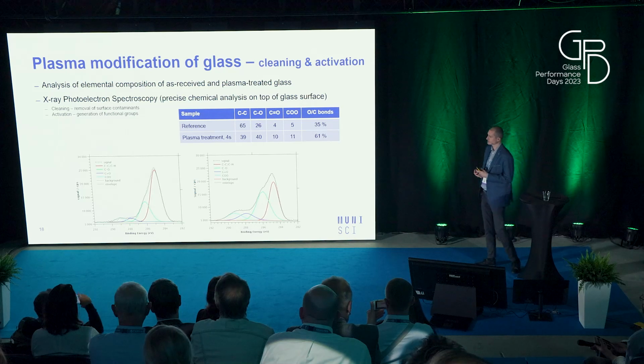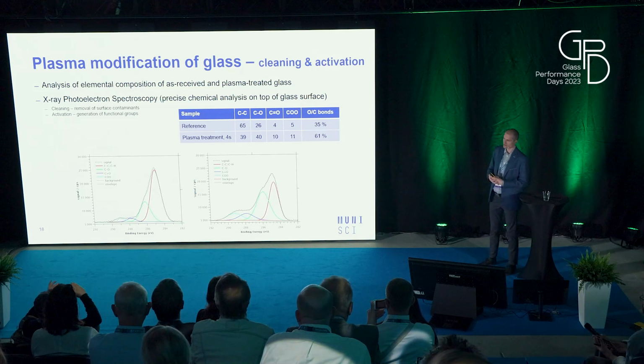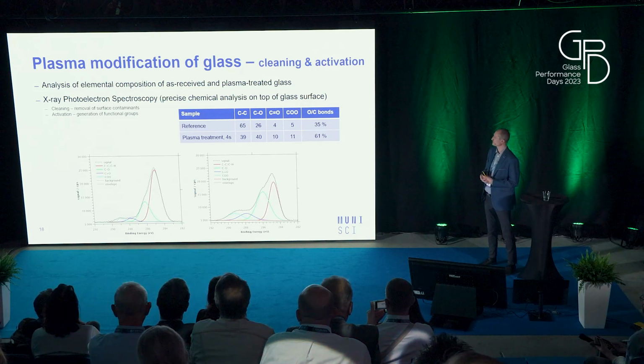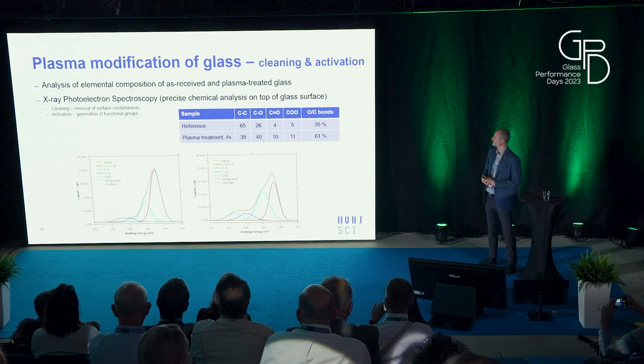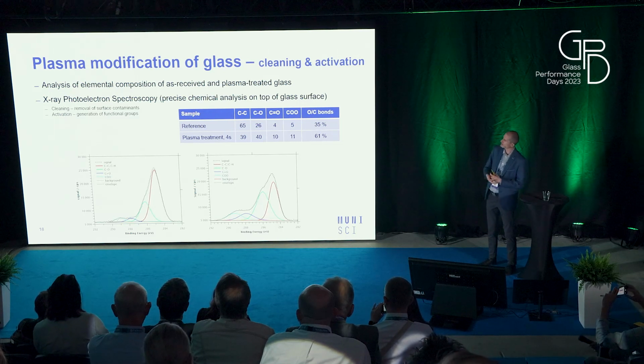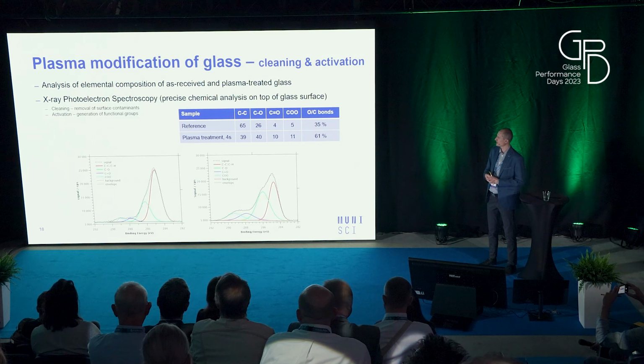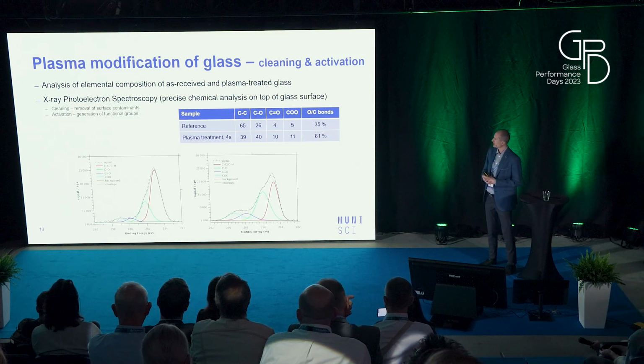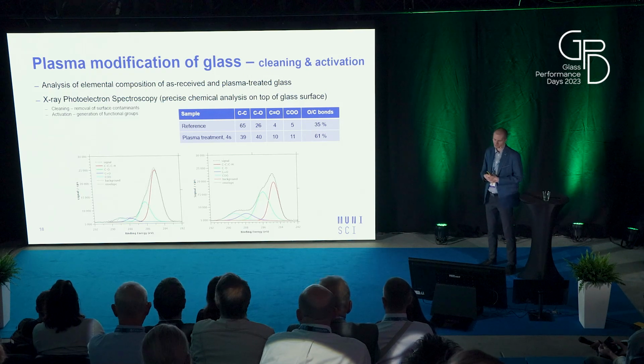Regarding the activation, because we not only clean the glass, but we also create some surface functional groups on the surface, we analyzed it again by the XPS method. We revealed the presence of these oxygen functional groups on the surface of glass.